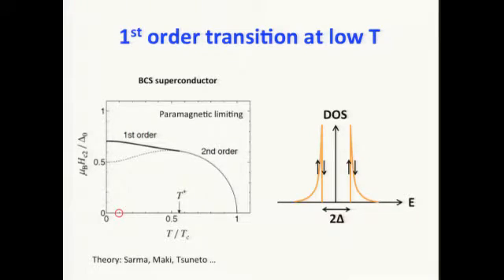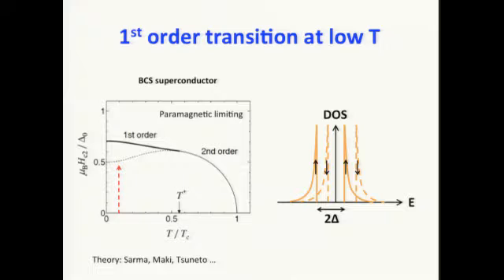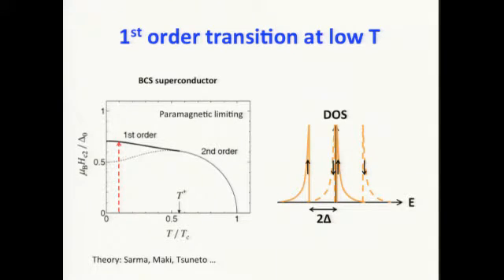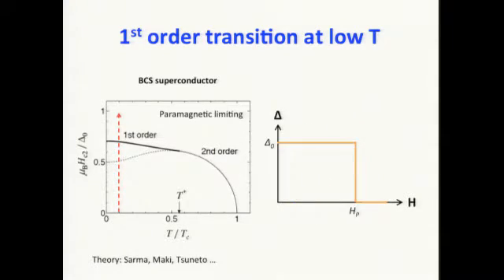This can actually be measured by tunneling measurements. If you do a tunneling measurement on a BCS superconductor, you can measure the density of states like this. You start from some low temperature, represented by this red dot here. As you increase the magnetic field, there's a Zeeman splitting of the quasi-particle density of states, so the spin up goes to the right and the spin down goes to the left. But I want you to notice that the superconducting order parameter, or the superconducting gap, remains unchanged for a BCS superconductor. If you keep increasing the magnetic field close to the phase transition line, the spin up and spin down quasi-particle peaks almost touch each other. When you go a little bit more, it suddenly jumps to zero. It's a first order phase transition.